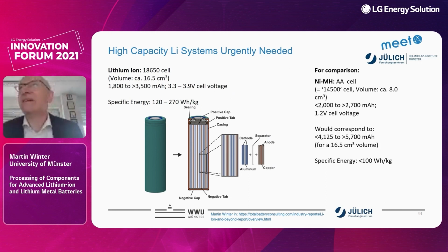If we take a nickel metal hydride cell, an AA cell, that's a different format. When we translate it into the same terminology, it is a 14500 cell with about half the volume of an 18650 cell. This gives us a certain capacity and a certain voltage, 1.2 volt cell voltage. If we normalize this capacity to the volume of an 18650 cell, so we take the same 16.5 cubic centimeter volume, this would correspond to a very high capacity of these nickel metal hydride cells. So nickel metal hydride cells have much higher capacities than lithium-ion batteries, but the specific energies are typically less than 100 watt hour per kilogram.